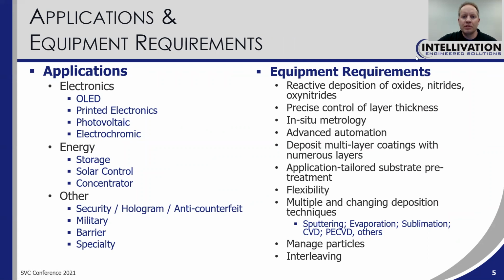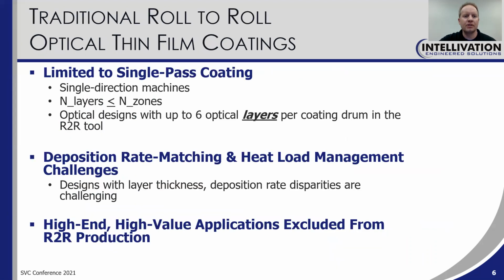So in terms of the requirements for the equipment used to create these types of coatings, reactive deposition of oxides, nitrides, oxynitrides at a high rate, precise control of layer thickness, in situ metrology, advanced automation, the ability to deposit multi-layer coatings with numerous layers, and frequently application-specific pretreatment of the substrate, flexibility of the machine. These requirements change over time, and just many requirements for these machines.